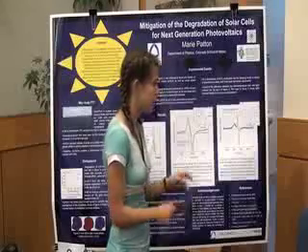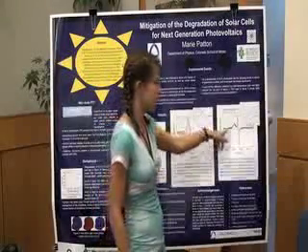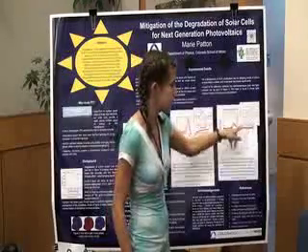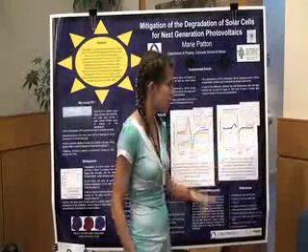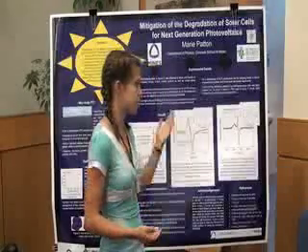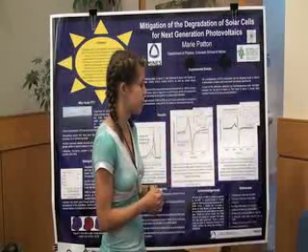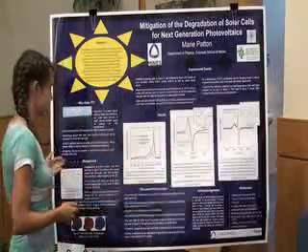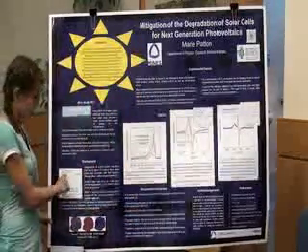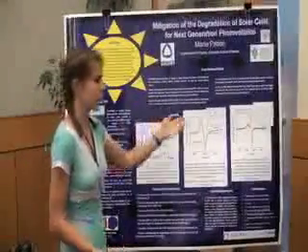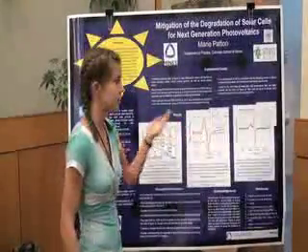As you can see here, this is due to the holes in the material, and this is due to the electrons. And this is when the carriers get stuck in the band tail states. So going back to this graph, the amorphous degrades a lot in sunlight because it creates more defects in the material, which is bad.